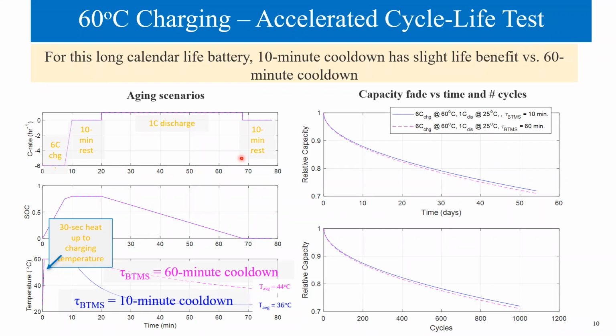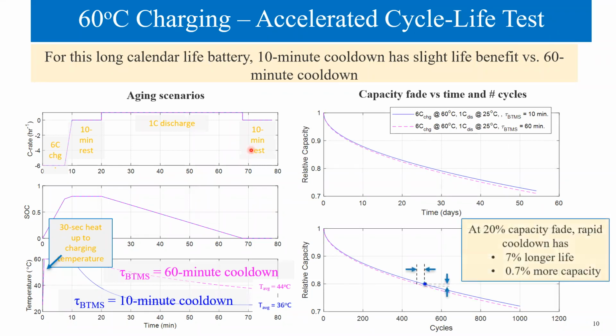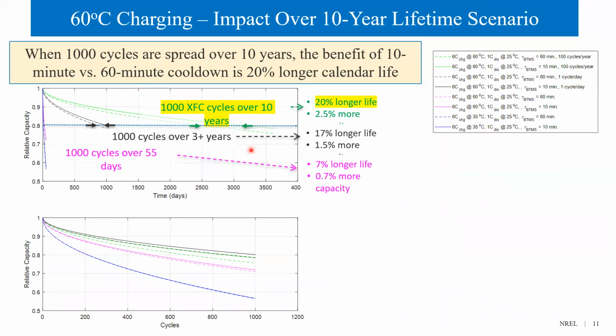For this long calendar life battery, during accelerated cycle life testing, 10 minute cooldown has a slight life benefit versus 60 minute cooldown. At 20% capacity fade, rapid cooldown has about 7% longer life. If we consider a real case scenario, for example 1,000 fast charges occurring over 10 years, 20% longer battery life can be achieved with rapid 10 minute cooldown.